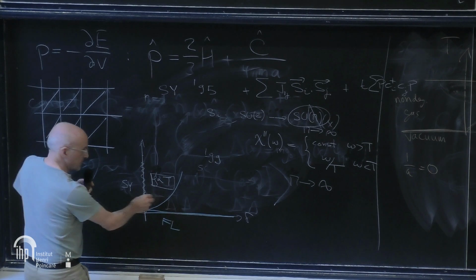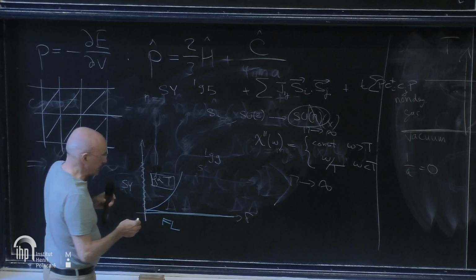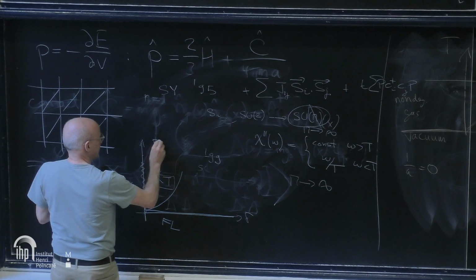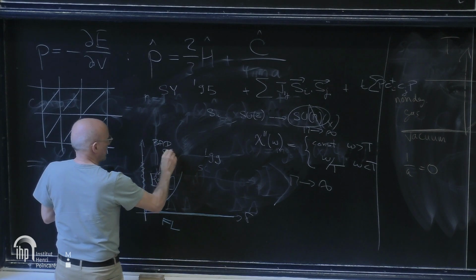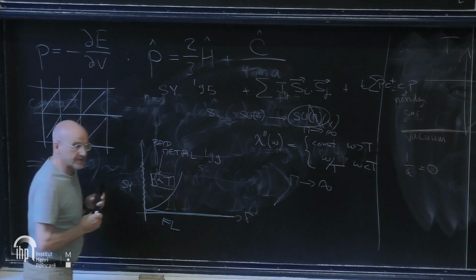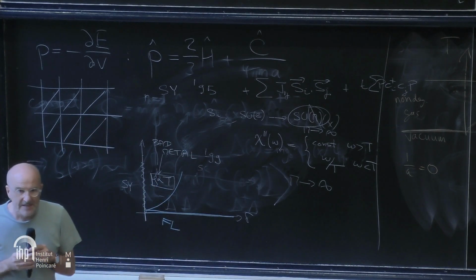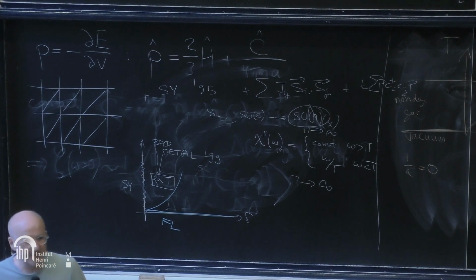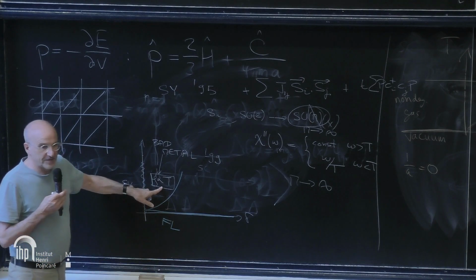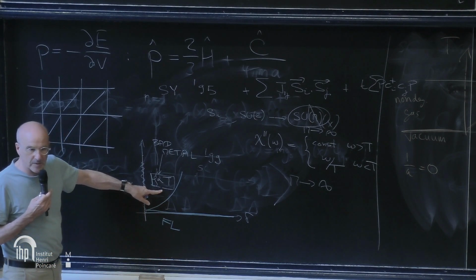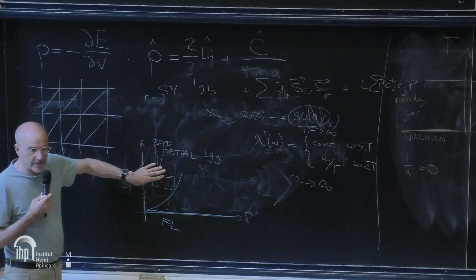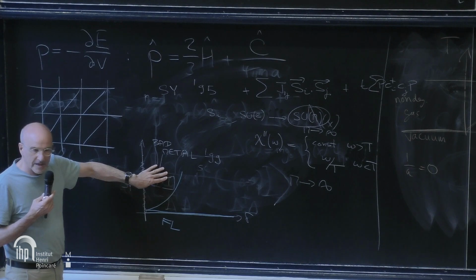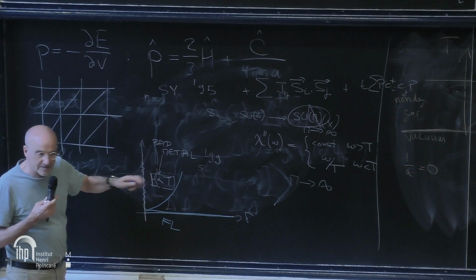So this is not a theory of a strange metal. This is a theory of a bad metal. It's quite important to understand the difference between these two things. The mystery of strange metals is that you can get T-linear resistivity in regimes where the mean free path is large. This is a theory of T-linear resistivity in regimes where the mean free path is comparable to the lattice spacing, which is more appropriately called bad metal, and there are many mechanisms for that.